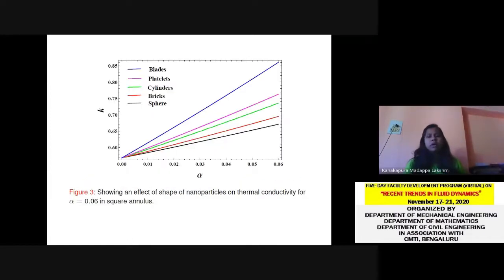Figure 3 is the plot of thermal conductivity versus volume fraction, and from the graph it is clear that the effective thermal conductivity of blade-shaped nanoparticles is highest compared to all other shapes. The reason behind this finding is that compared to all other shapes, blade-shaped nanoparticles have a large surface area, so the thermal conductivity in that case is more. Also, the blade shape offers the least friction for fluid flow.